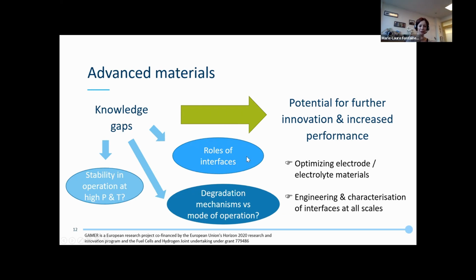We have seen already in the slide that I've shown you that they are impacting a lot on the performance, both the ASR, but also the Faraday efficiency. Both these criteria are very important for this technology. And where there is still an opening is how long-term degradation will happen. So this is still a question that we are working on with long-term stability studies. And we know that this will be impacted a lot by how we are going to operate the stack or the module, as we call it, whether we do steady-state operation or cycling.